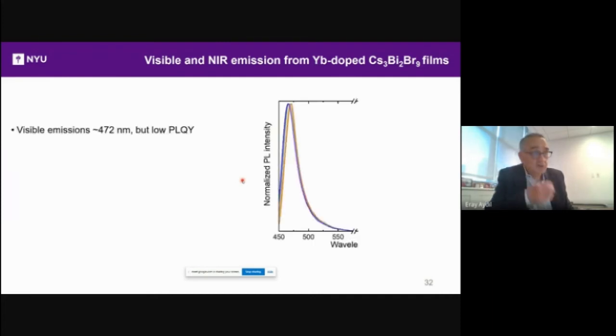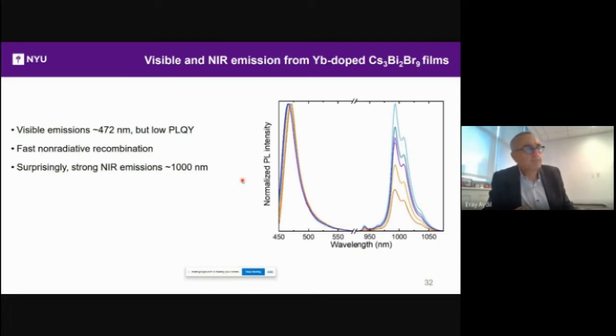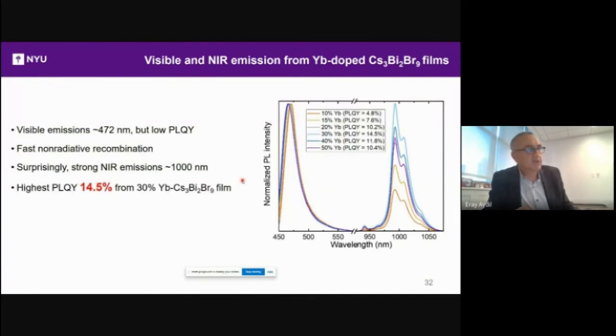So I'm going to show you visible and near-infrared emission from ytterbium-doped films. So first of all, visible emission at 472 nanometers. And recall that when people made the nanocrystals, the trustable data showed the photoluminescence quantum yield is weak, 0.2% at most. And we basically get the same result. It's a very weak photoluminescence in the visible. So that is a sign of fast non-radiative recombination, okay? However, there is surprisingly strong near-infrared emission at 1000 nanometers, where you would expect it from the ytterbium 3+ ions.